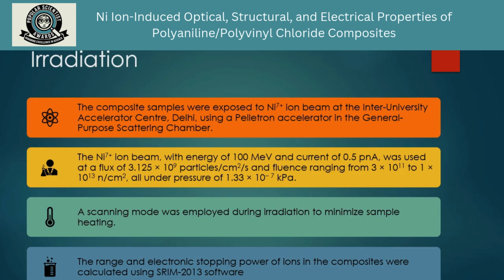of 3.125 into 10 to the power 9 particles per centimeter square per second and the fluence ranging from 3 into 10 to the power 11 to 1 into 10 to the power 13 particles per centimeter square was used. All this was done under the pressure of 1.33 into 10 to the power minus 7 kilopascal. The beam was used in the scanning mode so that to reduce the chances of heating of the sample.